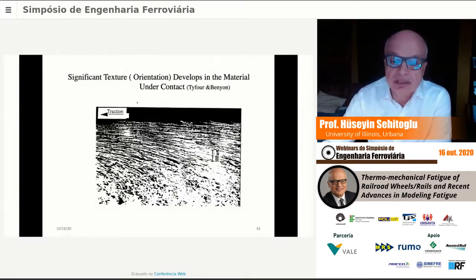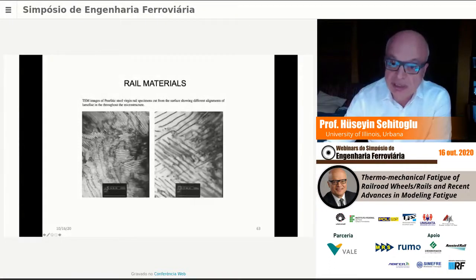And the material that was straight here initially is now curved, because there is a considerable amount of shear strain here, right? This is ratcheting. Sometimes it's called texture. Material gets oriented as well. The grains get oriented that way. Again, more or less, these are similar materials to wheels, perhaps a little higher carbon content.